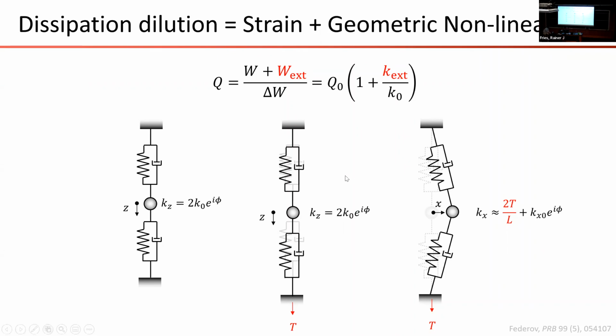However, if you have something called a geometric nonlinearity, you can engineer a lossless spring by tension. So if I take this two-spring system and stretch it with a static tensile force, and you can imagine doing that by, for example, mass loading this spring in a gravitational potential or using some sort of thin film stress, then the restoring force for a transverse displacement of this mass has a term which is due to this tensile stress that's purely conservative. This is called a geometric nonlinearity. And if you believe that this tensile stress has no time delay associated with its response, then that geometric nonlinearity gives rise to this lossless spring effect and dissipation dilution.